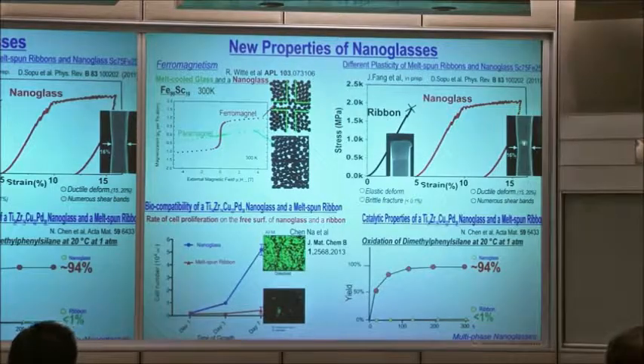So these interfaces act as nucleation sites of many shear bands, but very tiny, short ones, and they're stopped immediately. They can never build a big shear band to fracture. It's like the deformation of a polycrystal in comparison to deformation of a single crystal, where you have one big slip plane that fractures, and here we have numerous fine slip planes. And you can see that. Can you see what happens to the glass? It uniformly deforms, and on that surface, if you look in the electron microscope, it's an almost uniformly sheared region. It looks like a piece of copper.